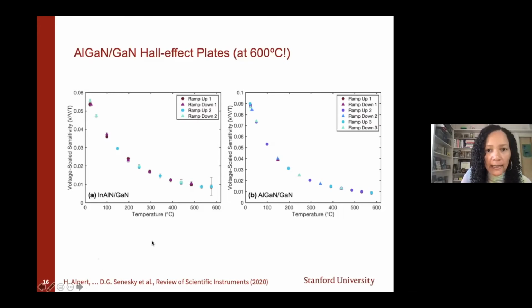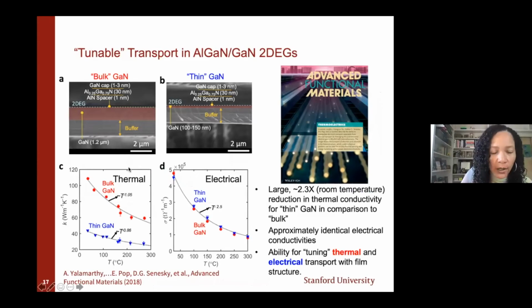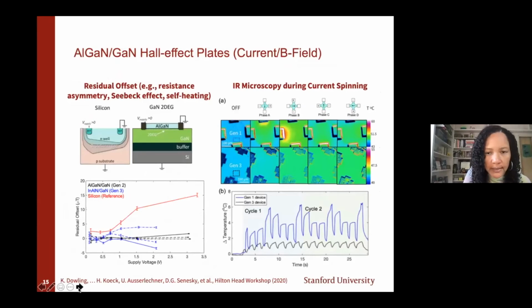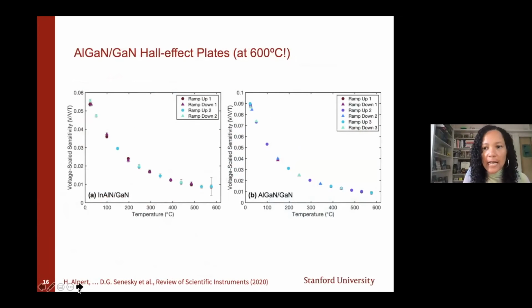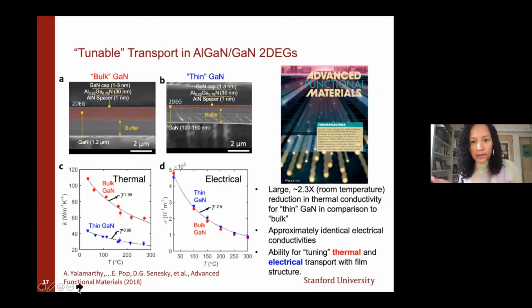Again, thermal cycling, I would say these are minutes of cycles, right? We haven't quite done hundreds of hours yet on this particular device in that work, but later on we have done more extensive studies, and that's something that's ongoing. So I mentioned the Seebeck effect, right? We're trying to get rid of this Seebeck effect. We want to minimize the offset voltage. But the Seebeck effect is also something you can use to create energy harvesters.